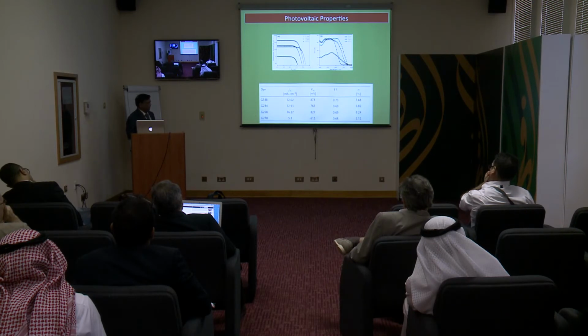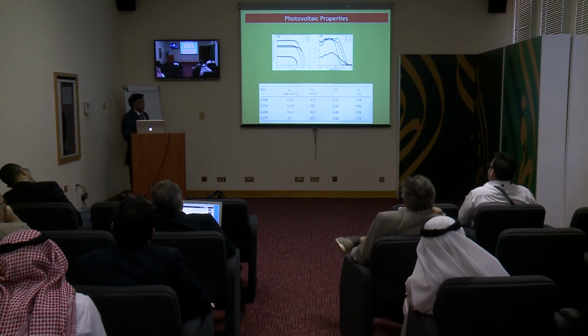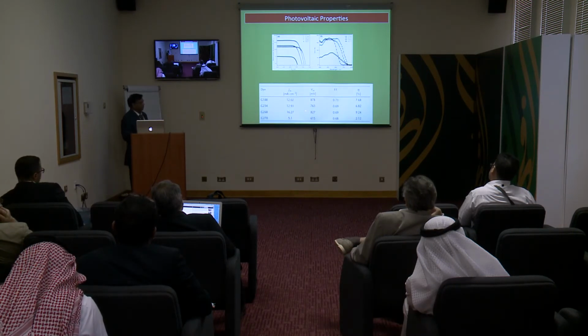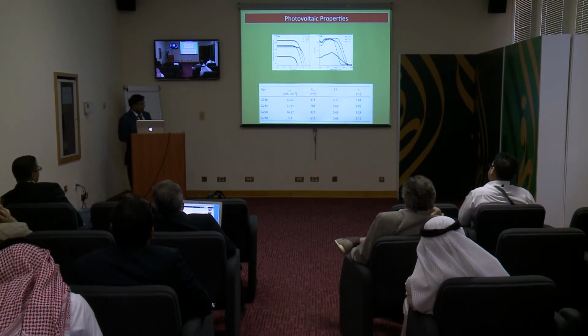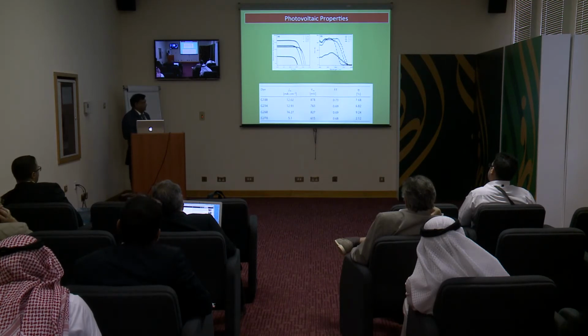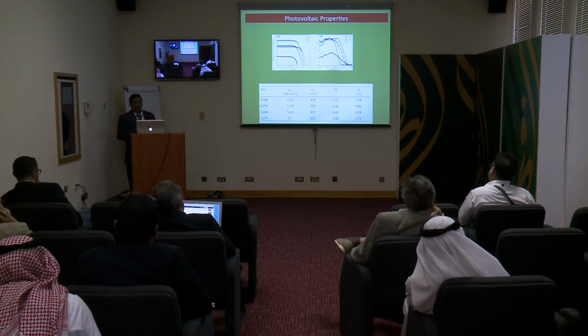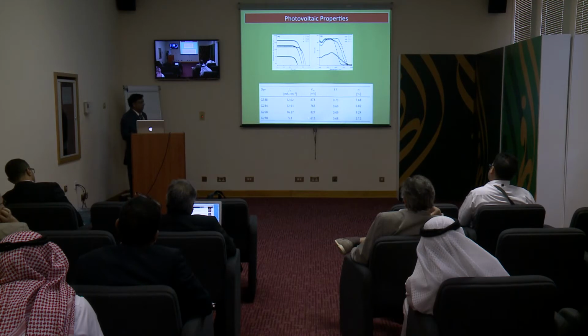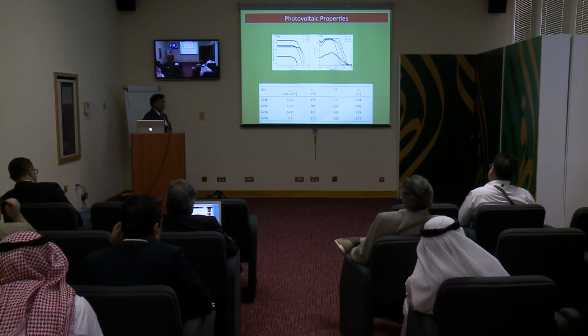First, if you can see this 268, which has an 80 nanometer redshift in the absorption spectra, it has the highest current. It's around 16 milliamps, and then there is a very small drop in the VOC, and that gives you the highest performance, more than 9%. In the case of this other one, as we have seen, there is a small difference between the HOMO level and the energy of the electrolyte. It could have hampered the dye regeneration. In fact, that's what we see: only 5 milliamps of current, and also low potential, which results in just a 2% efficiency.